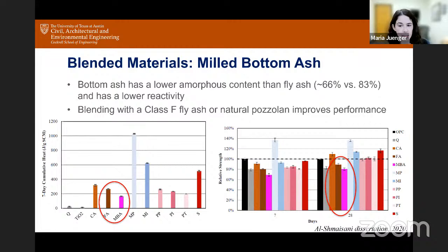In this particular example, the amorphous content of this bottom ash is about 66%, and the amorphous content of the fly ash is 83%. The bottom ash has a lower reactivity. So again, aren't you just so impressed that I keep showing the same graph over and over again? I just keep dumping the same material at you, but highlighting different aspects of it.